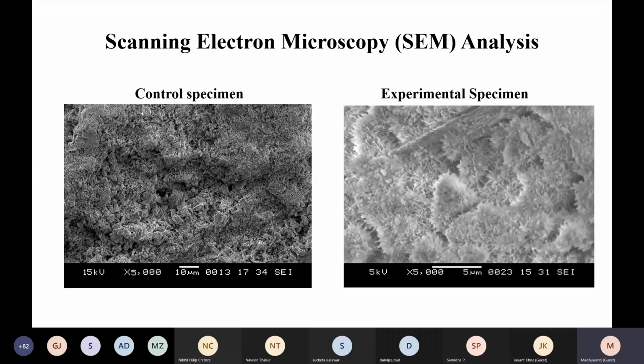Also, the experimental specimens were subjected to various durability tests like chloride analysis, sulfate analysis, then carbonation test, then RCPT, and it was to our extreme bliss that the experimental specimens in fact were better in terms of durability than control specimen. Now I am not presenting those results here because that will be too long a data to present. I am just telling you. Again I am saying that you can see my publications in which we have presented all the data.